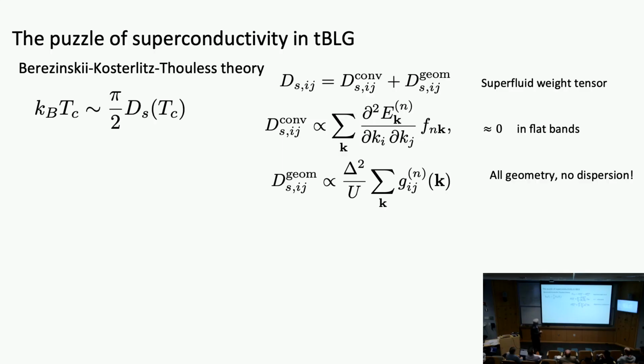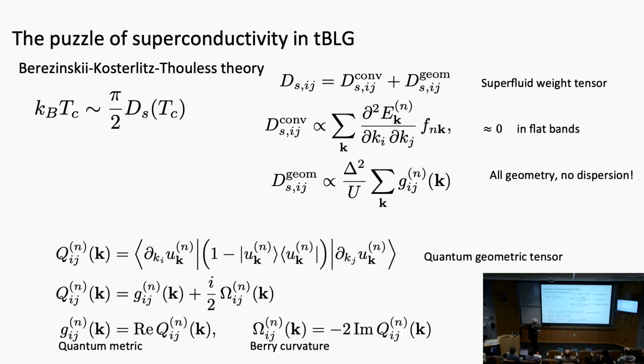And this tensor basically has two contributions. One is the conventional contribution, which comes from the curvature of the bands. This component of the tensor is proportional to the second derivative of the bands. But if you have completely flat bands, there's no curvature, so this component of the tensor vanishes. So all you have is the other component of the tensor, which is called the geometric component, and is proportional to this tensor. So this is all geometry if there's no dispersion. And what does that mean exactly?